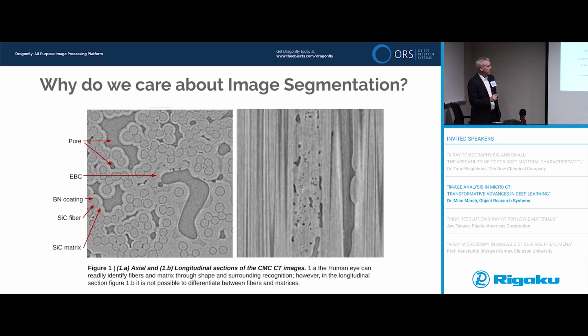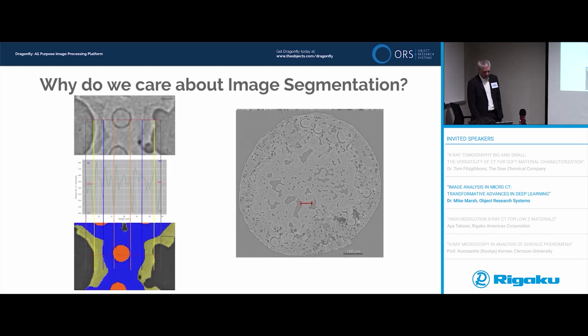So in order for us to characterize the fibers or the matrix thickness or the porosity, we have to segment it. What we're looking at here is an axial section, and what we're looking at here is a longitudinal section of exactly the same material. It looks quite different when you look at it on end, but in either case, the segmentation is very challenging.